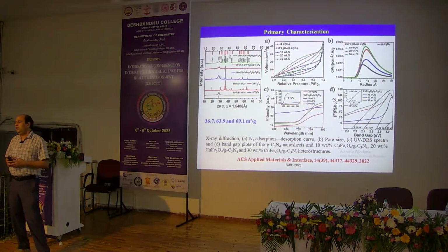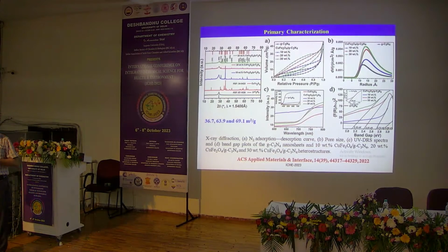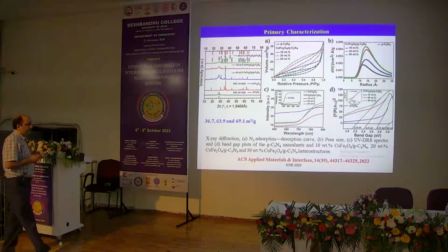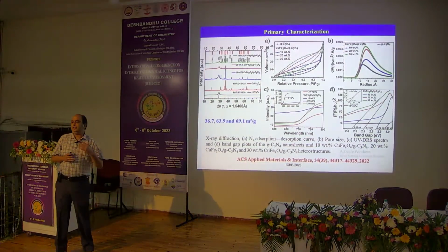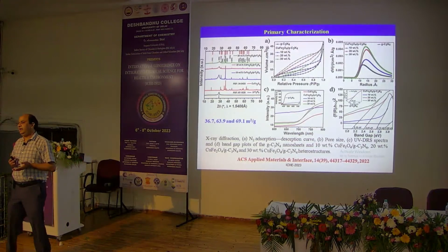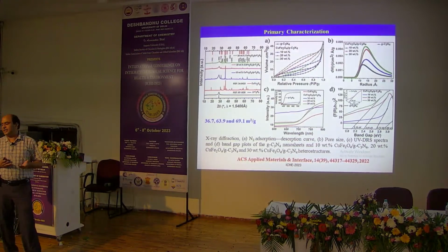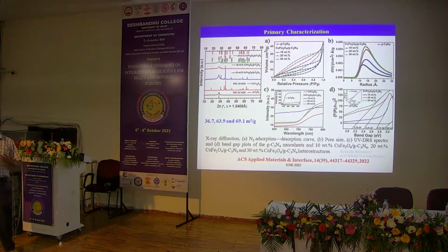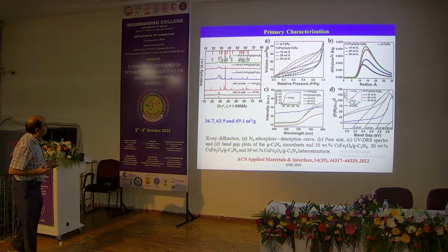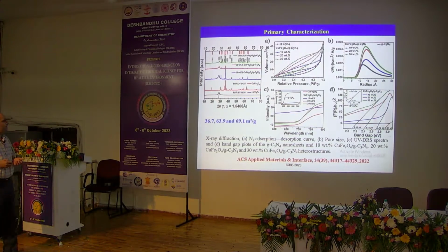Initially we do the primary characterizations like the BET surface area and the detailed UV-visible DRS study for the optical band gap, and if you have a good understanding of X-ray diffraction, then you can easily index each and every reflection, and you can confirm whether you have the heterojunction formation of copper ferrite with the graphitic carbon nitride.